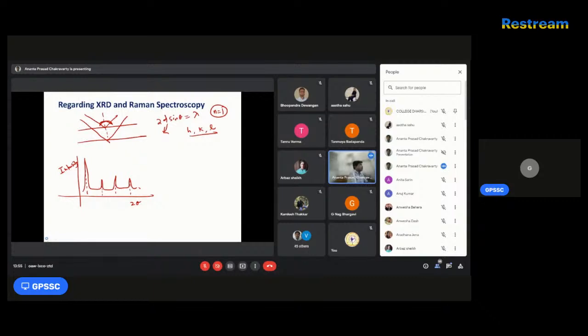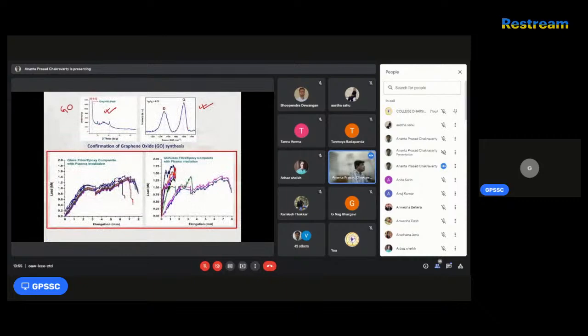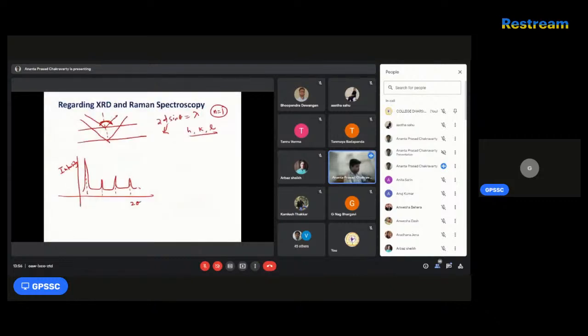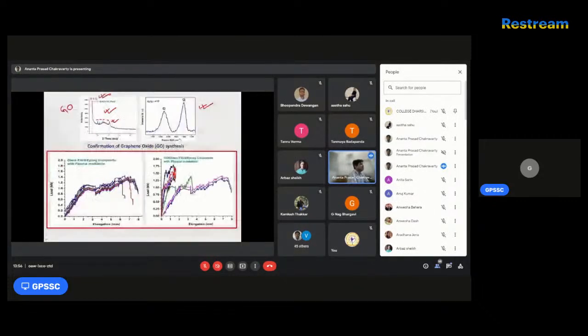So generally for your graphene oxide, you can see at 10 degree a 001 index will come, and at 40 degree one peak is coming, and all these are some impurity peaks. Similarly, Raman spectroscopy is associated with vibrational spectra. When you keep the sample in the Raman spectroscopy, you can obtain some vibrational spectra in different bands, and those bands, the D band and G band, are very crucial for these graphene carbon based materials, typically in graphene oxides or reduced graphene oxides, or in graphene as well. Generally in GO, the intensity of the D band to the intensity of the G band must come around 1, but for my sample, it is laboratory based synthesis, which is 0.72.